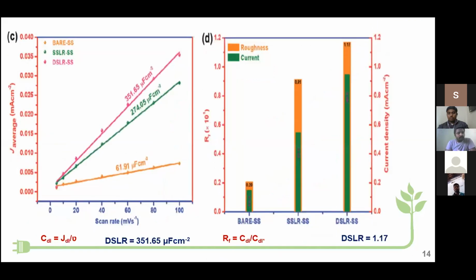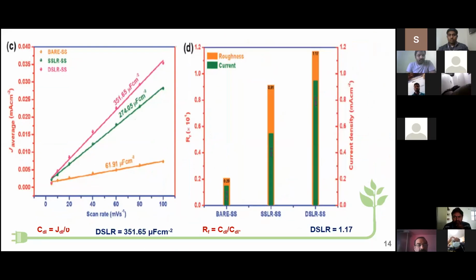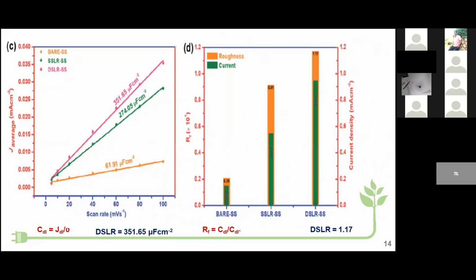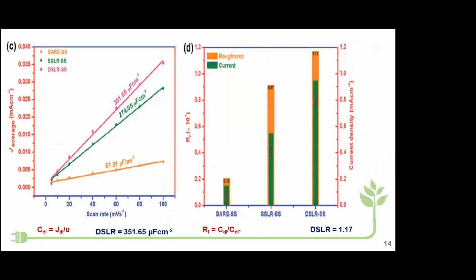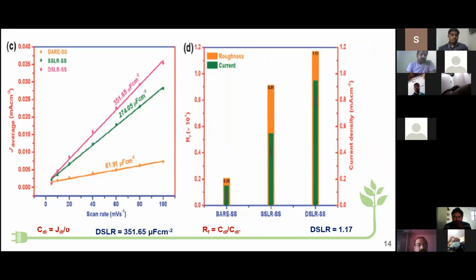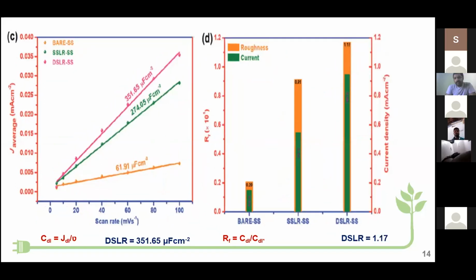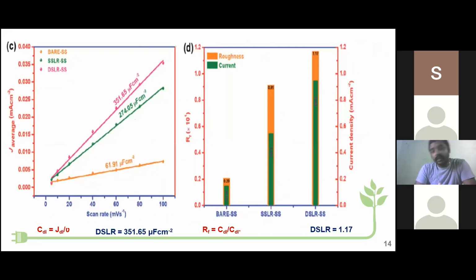Figure C is for the calculation of double layer capacitance using the following equation: C_DL equals J_DL divided by nu, that is, current density divided by the scan rate. Here also we achieved the same trend: double side laser irradiated stainless steel exhibits a higher double layer capacitance of about 351 microfarad per centimeter square. Using this double layer capacitance, we can determine the roughness theoretically using the formula RF equals C_DL divided by C_DL of the smooth surface. For example, smooth stainless steel has 30 microfarad of double layer capacitance. This is the experimentally calculated one. Again, the double side laser irradiated stainless steel gives a high exchange current density as well as roughness value.